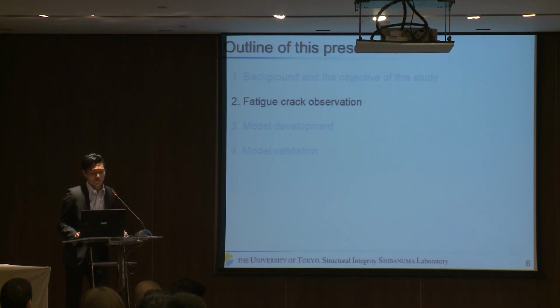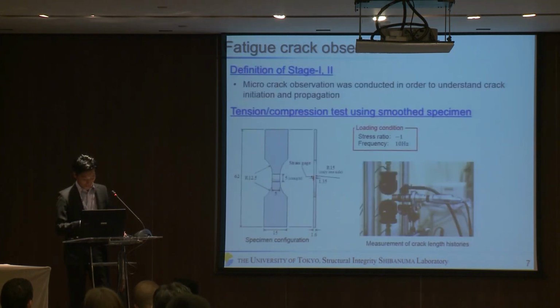Okay, so next, before a model is developed, stage 1 and stage 2 should be clearly defined. So in order to capture the early stage of crack initiation and propagation, fatigue tests and observation were conducted. So the condition of the test is shown here. In this experiment, tension and compression test is conducted, and the specimen is with a gentle notch in one side, so that the crack initiation side can be easily predicted.